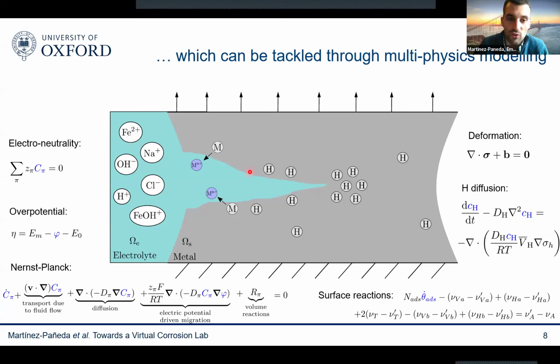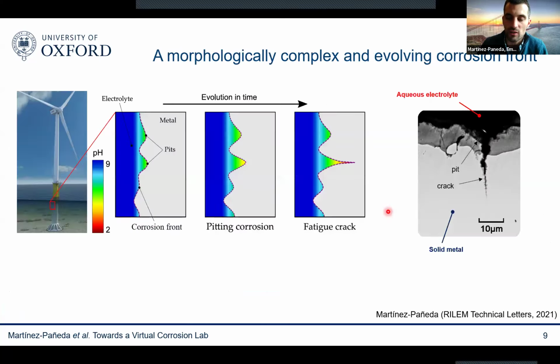The other challenge, of course, is that this picture is, in reality, not stationary. This defect, this pit, this crack is going to be evolving in time. And as this thing evolves in time, all of these things are going to be affected. So it's a complex multiphysics interfacial problem where we have an evolving interface, and capturing the morphology of that evolving interface is critical. You can see it here, by the way, in an example related to an offshore wind turbine monopile. In fact, corrosion fatigue, what you see here in offshore wind turbine monopiles, is the reason why these monopiles need to be retired after only 25 years. So we are actually working with wind turbine operators to develop more mechanistic models to see if they can extend the lifetime of these structures.